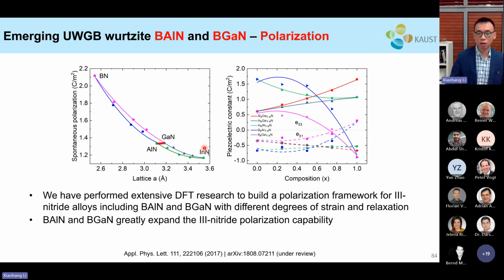Conventionally, people have done a lot of polarization engineering for the indium aluminum gallium nitride. So far, I have counted about 150,000 papers published with the keyword polarization for the III-nitride. Okay, so there are a lot of papers. But according to our research, we have found that by adding boron into this system, we can greatly expand the spontaneous polarization as well as the piezoelectric constant, so that we can actually utilize the BGaN and BAlN to create additional polarization engineering properties.